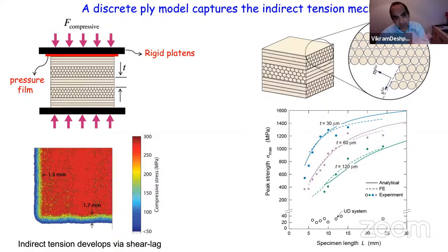And we can use the same kind of crystal plasticity framework for each ply that we had earlier. I won't dwell much on that, but the peak strength agrees relatively well with the experiments over different ply thicknesses, because the shear lag effect means ply thickness matters, and specimen length. So, we think we have an understanding of the problem.